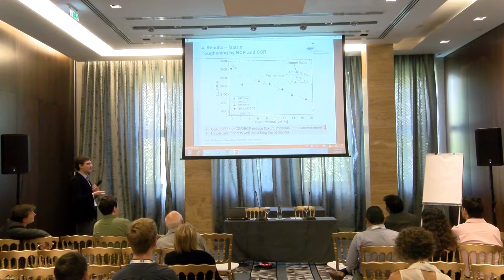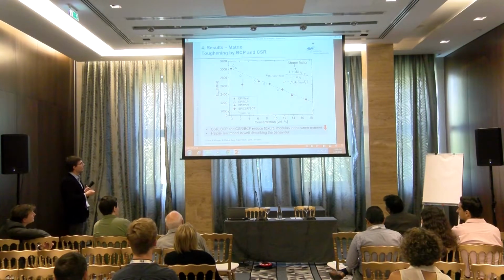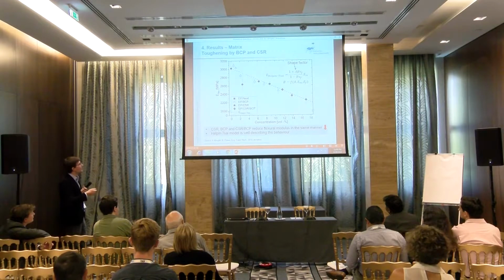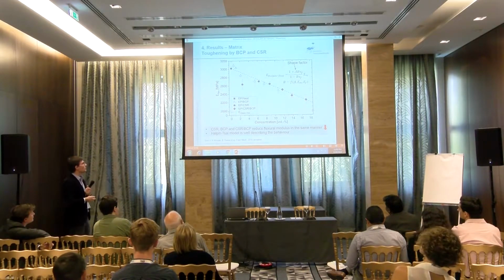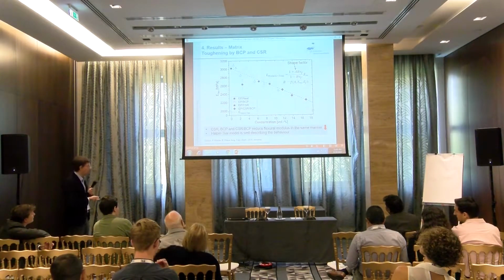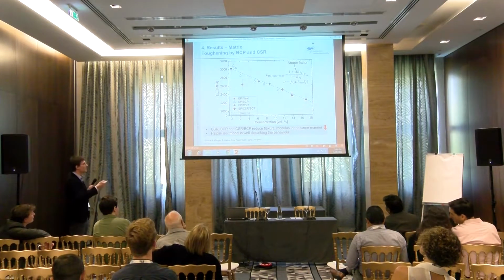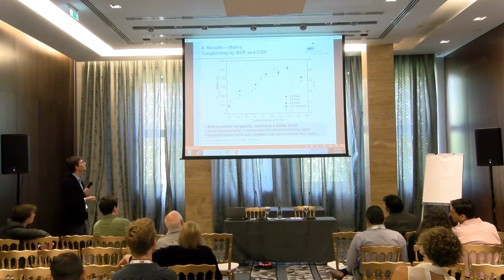In this graph, you see the flexural modulus. On the x-axis, you can see the overall concentration. And what is important is that, no matter what modification you use, it simply depends on your rubbery phase: your stiffness is decreasing. Additionally, it could be nicely modeled by using the Halpin-Tsai equation, which is for sure fitted in the end, or is a kind of fit that you can use.